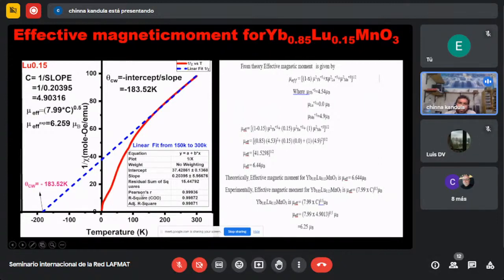From this curve, the linear part is around 150 to 300 Kelvin. I took the linear part and plotted it here. It touches the axis around minus 183.52 K, which means it shows antiferromagnetic nature at very low temperature. From that, I calculated the Curie constant, the effective magnetic moment, and the Curie-Weiss constant also. I got the Curie constant around 4.90316, and the effective magnetic moment and Curie constant are related by this expression I took from the literature, based on the Langevin theory of paramagnetism.